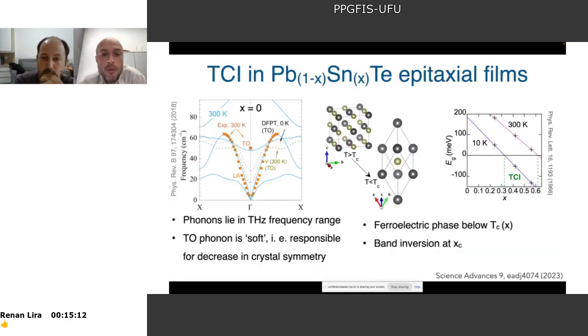Okay, so the system that I want to use to demonstrate the relation between chirality and topology is this topological crystalline insulator, which consists of lead, tin, and telluride. We study epitaxial films. It means that those films are grown by molecular beam epitaxy. And why this material? So this material is very interesting, first because the transverse optical phonon lies in the terahertz frequency range. It means that it can be accessible with current instrumentation using terahertz time domain spectroscopy.